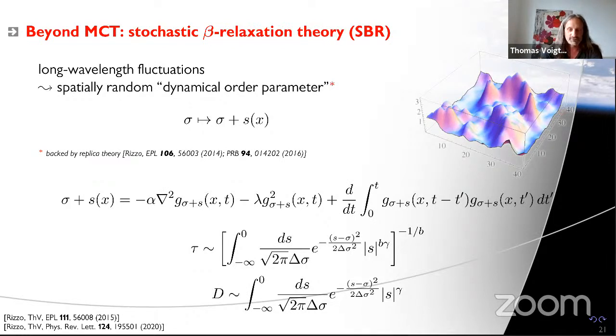Actually, intuitively, it's clear: if I quench the system into the glass, so on average the dynamical order parameter will be glassy, I will always find, however rare, fluctuations that locally mean that the system has a local liquid-like patch. And according to the theory that we developed, the prediction is that these liquid-like regions trigger relaxation and therefore prevent complete dynamical arrest. So the relaxation time diverges in the ideal glass, but if you include fluctuations in this way that Tommaso suggested here, the relaxation time will never truly diverge.